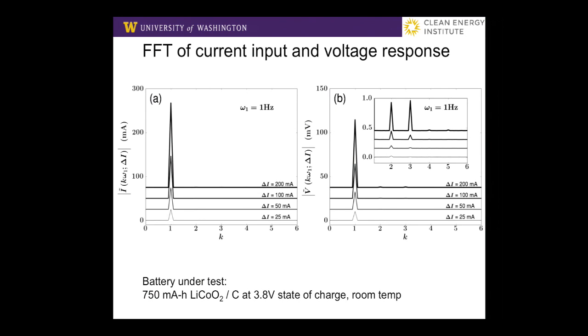And then at higher harmonics, K equals 2, K equals 3, and so on, we can see growing as we increase the modulation amplitude. We see a growing second and third harmonic at twice the frequency, 3 times the frequency. We can even see as we go to higher amplitudes, 4 times the frequency, 5 times the frequency. There are these nonlinear harmonics.